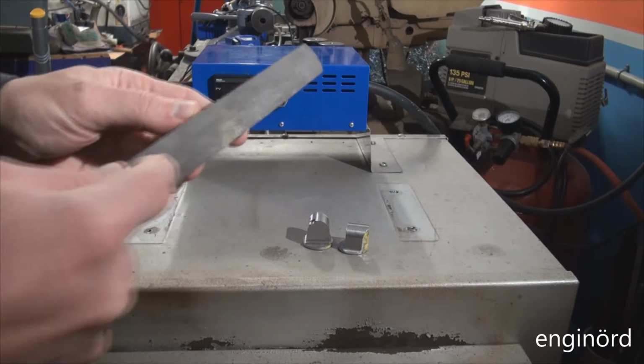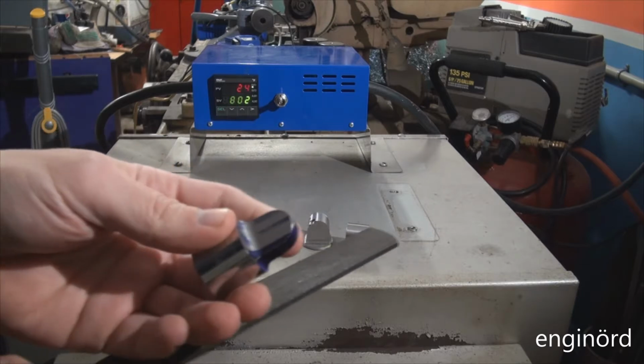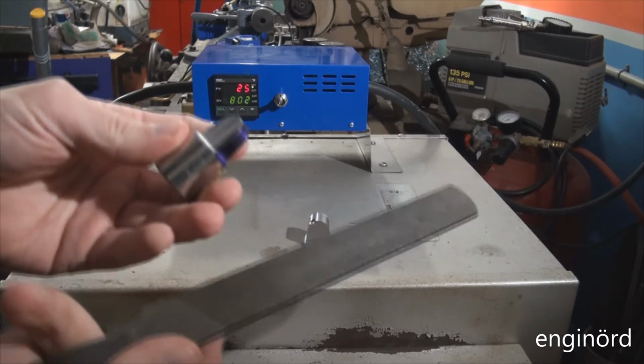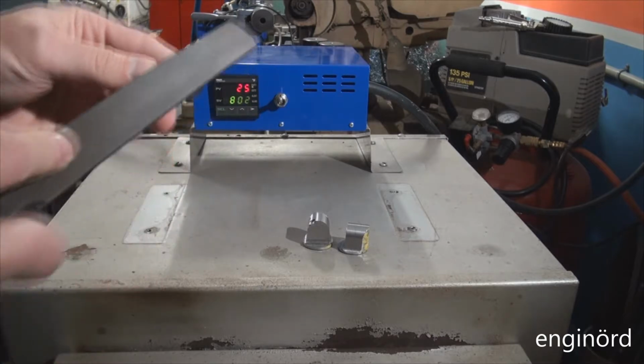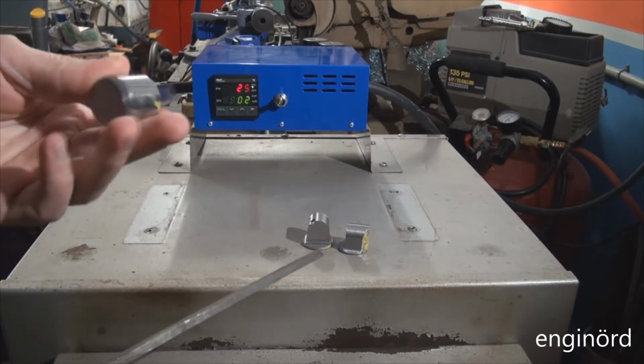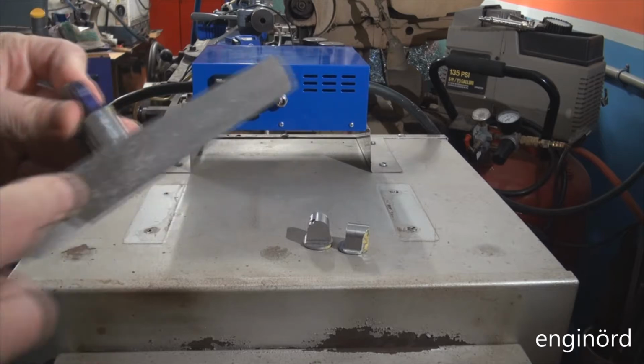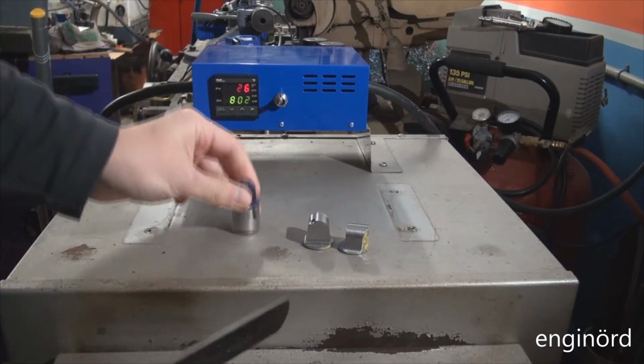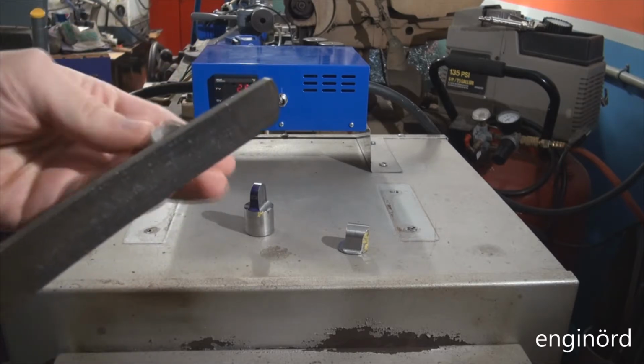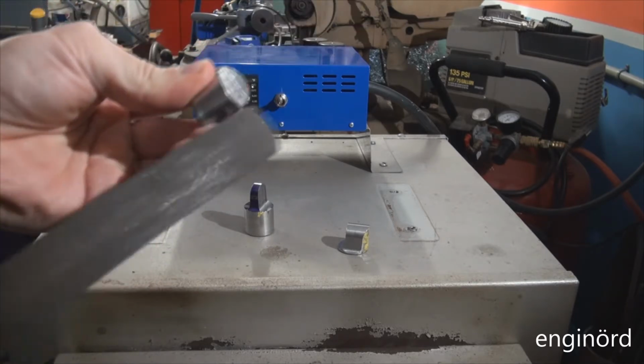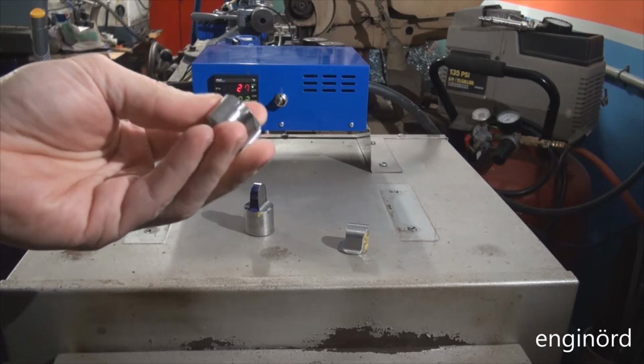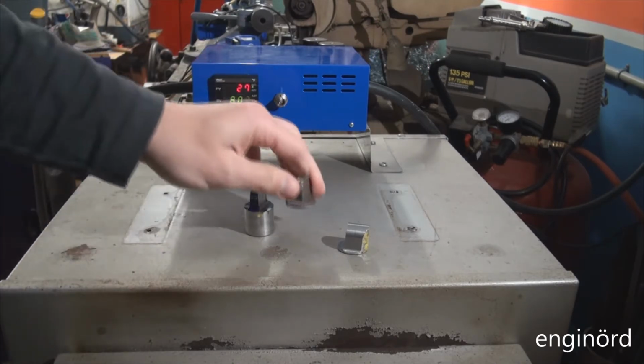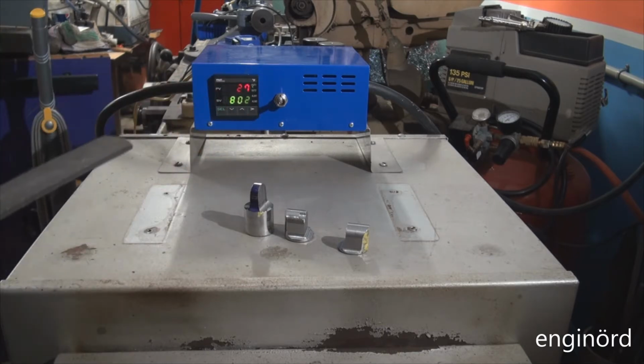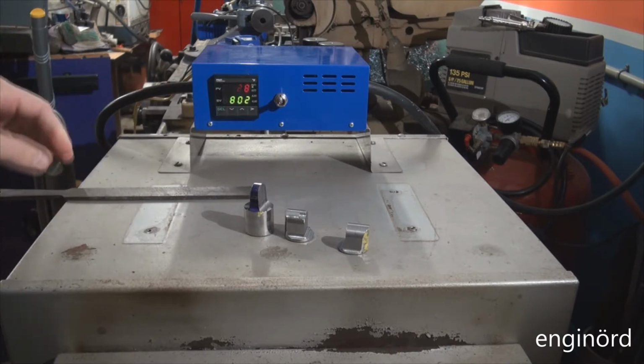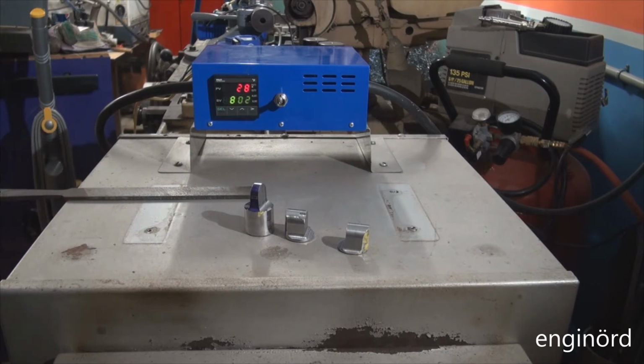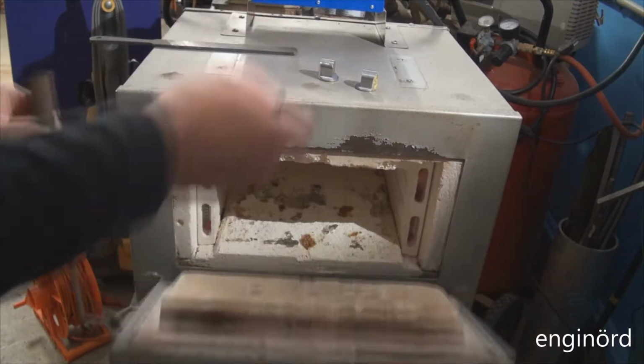As you can see, it's still in a soft annealed state. The file is gonna cut it, and what we're gonna do is use these as test coupons and do a heat treating cycle. So first we're gonna heat it up to 802 degrees Celsius, and then we're gonna quench it in oil. So let's bake some O1 tool steel.